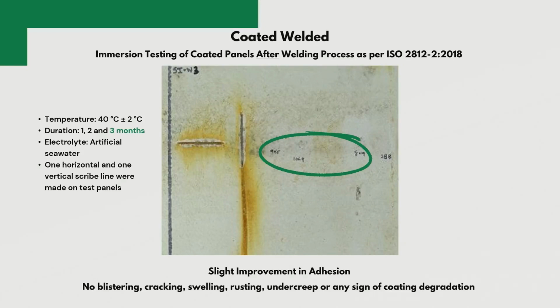Yeah, just a quick one. Any test results on how this coating performs in an MIC environment? Another good question. First, realize that what makes MIC is it forms an acid, right? The microbes form an acid. That's why microbial corrosion is severe, it's acidic. What's really interesting about this technology, pitting corrosion is also acidic. So if we miss a spot when we're spraying, and we don't get all of the grit out of the profile, it will start to bleed. When it does, the ceramic just extinguishes it.